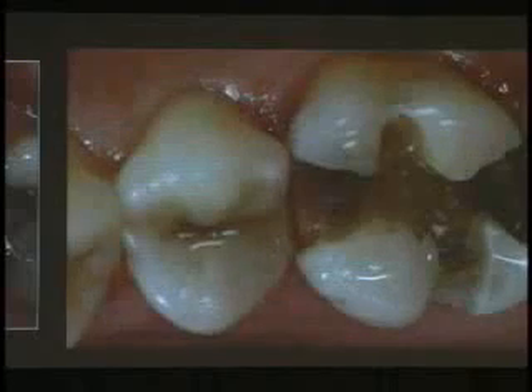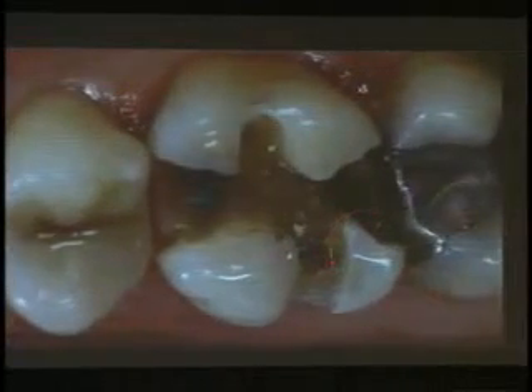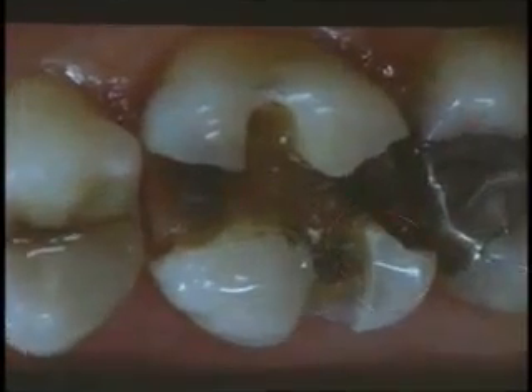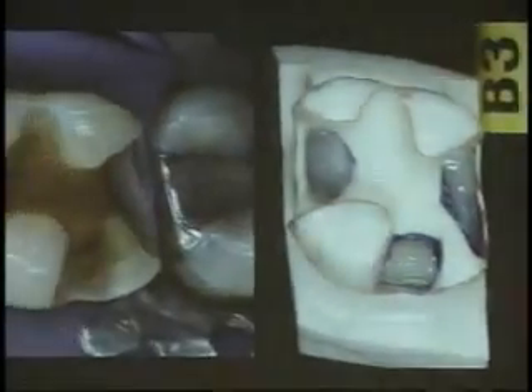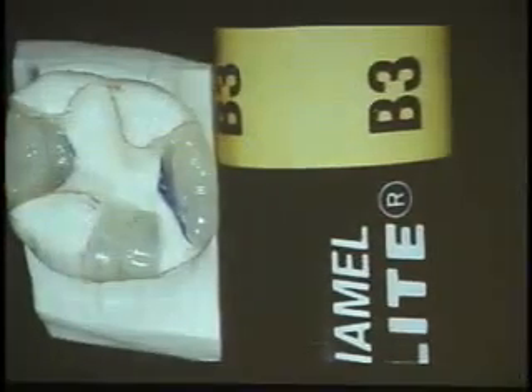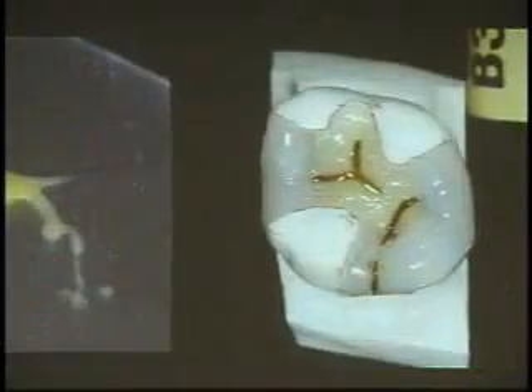That's another example. Here we have a cracked cusp, you see here. In that case, because it was so thin, we decided to overlap that cusp with the restoration. We still decided to go with composite, so the shade was a B3. We go with a little more saturation inside, a little bit of opaque dentin to mask this very strong staining here, and then build up the ridges in enamel, a little more saturated in the center, and then a little bit of stain, of course, and then the ridges one by one.